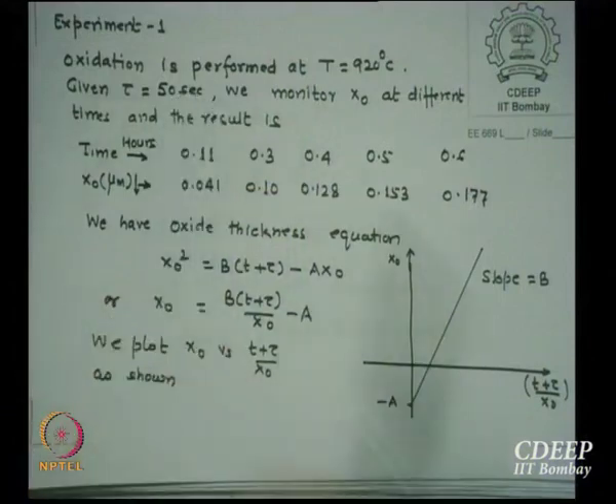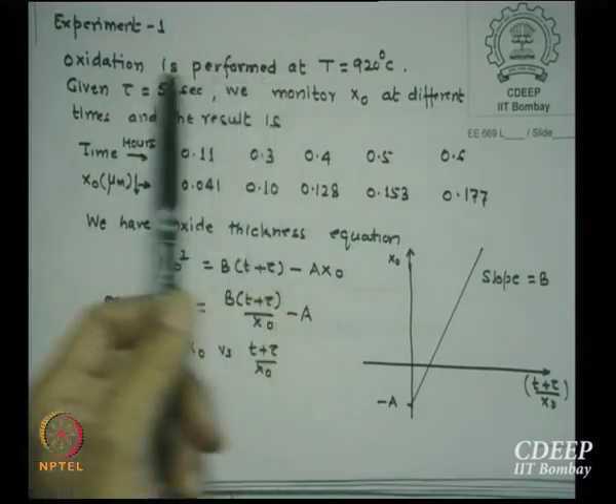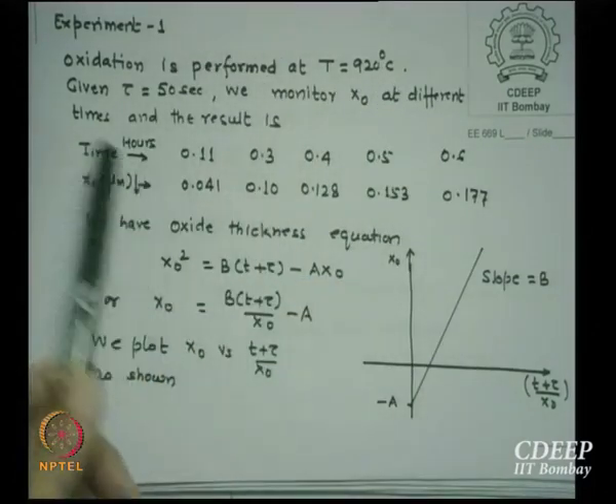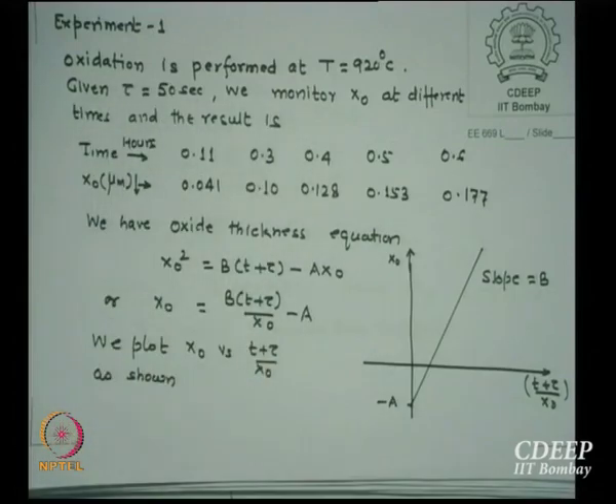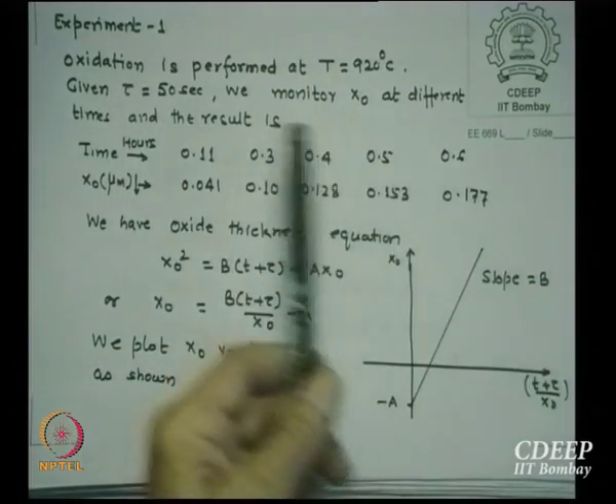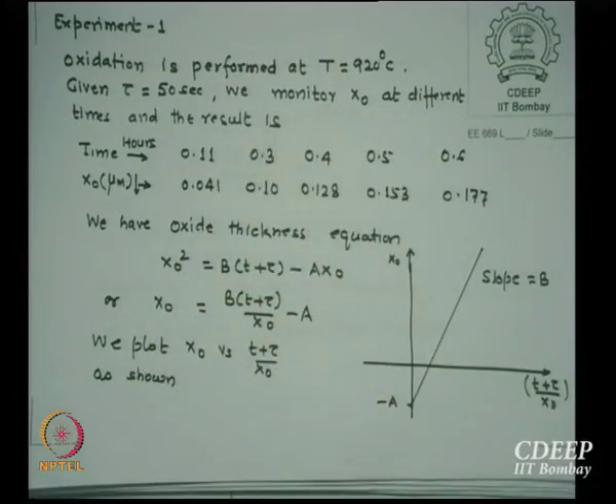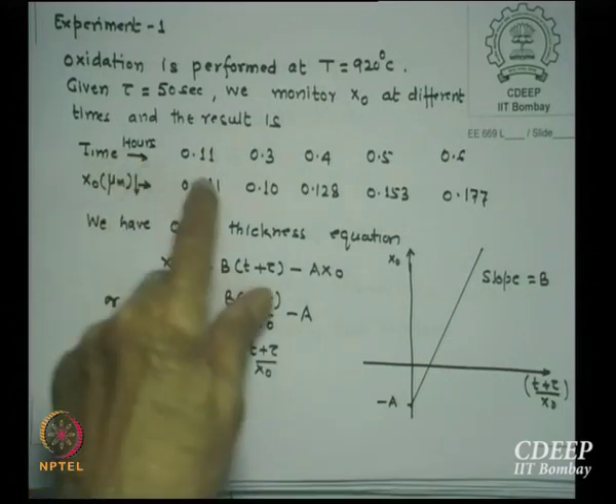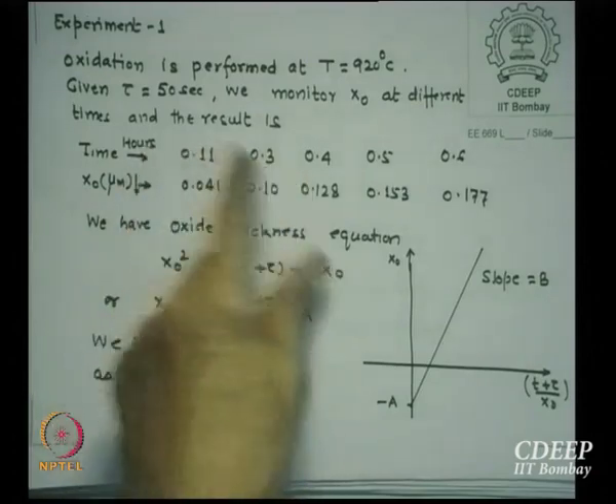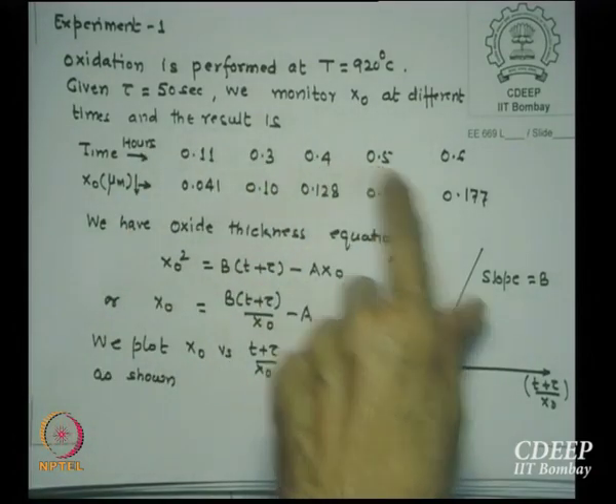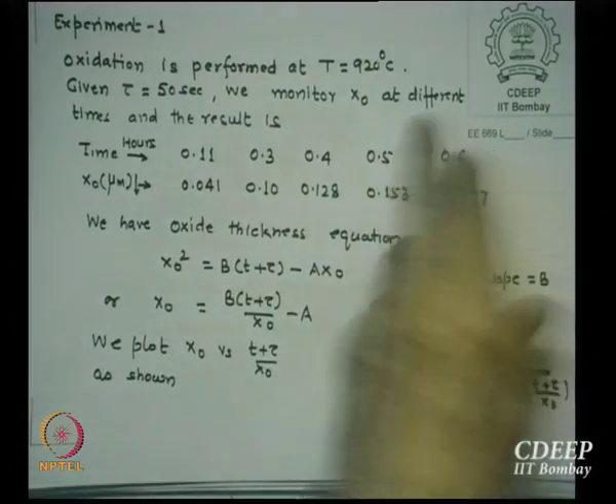Here is an experiment that was performed, just to compare those values which I am talking about. I have done an oxidation experiment, meaning an actual experiment was performed. I have grown an oxide of silicon at 920 degrees centigrade and assume that tau given to me is 50 seconds. Now we monitor x0 at different times. I keep growing, 5 minutes, time in hours. So this is some 6 minutes, and this is 18 minutes, this is 24 minutes, this is 30 minutes, this is 36 minutes, roughly 40 minutes.